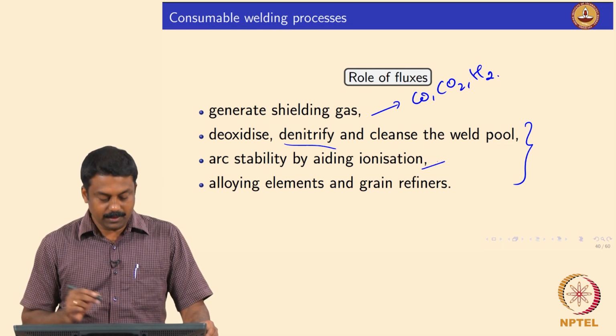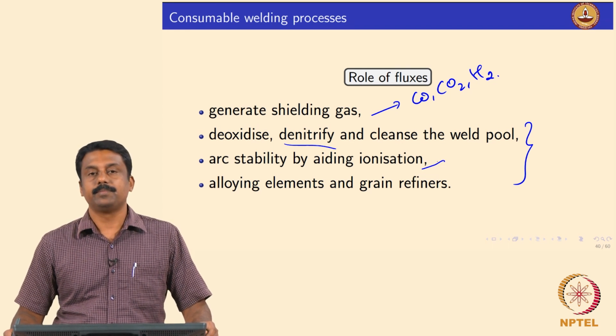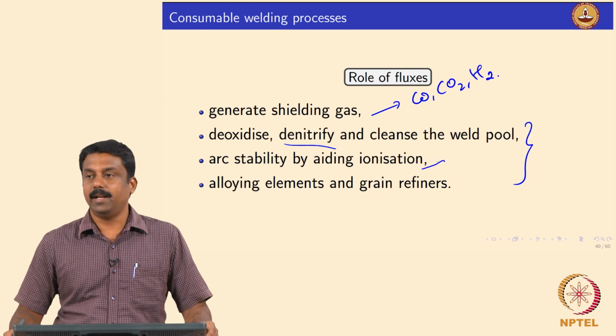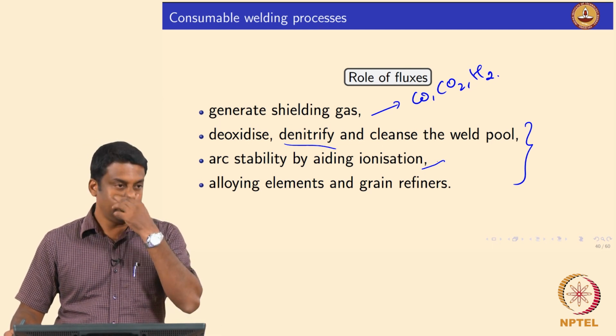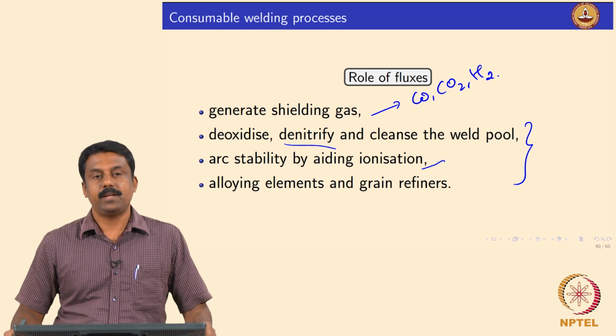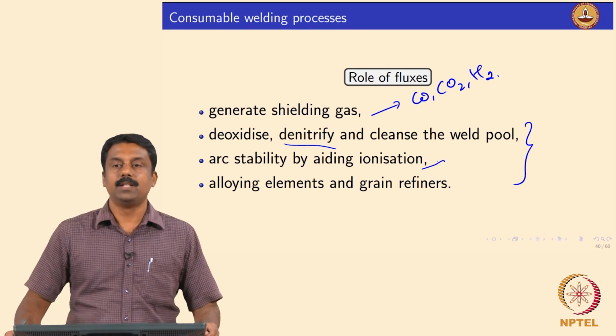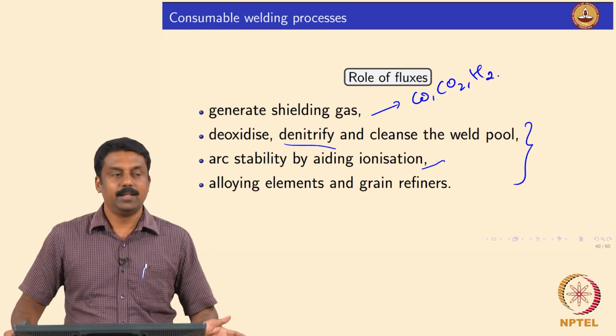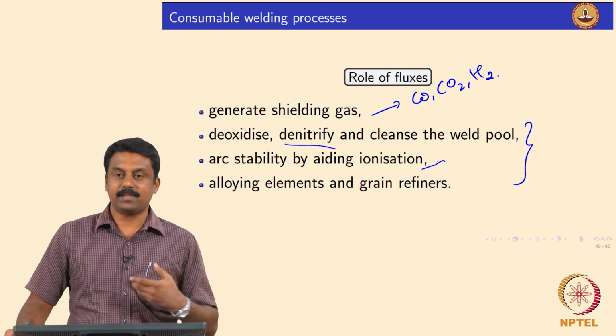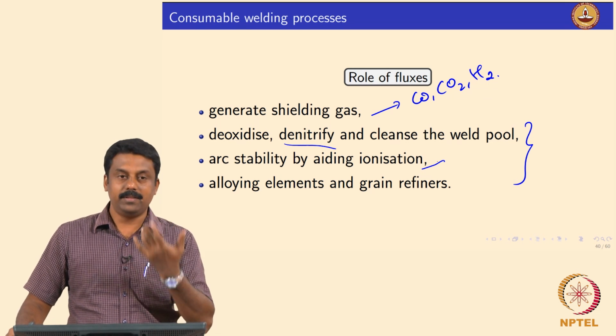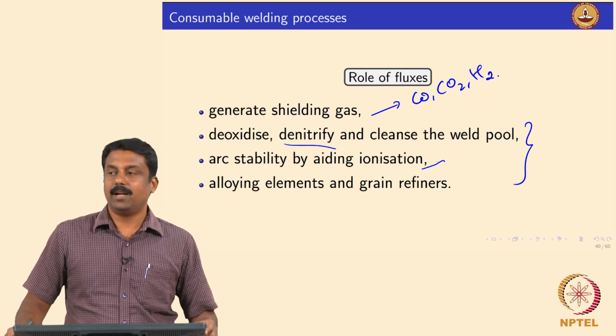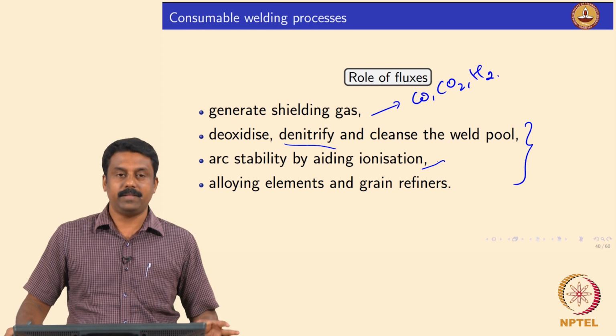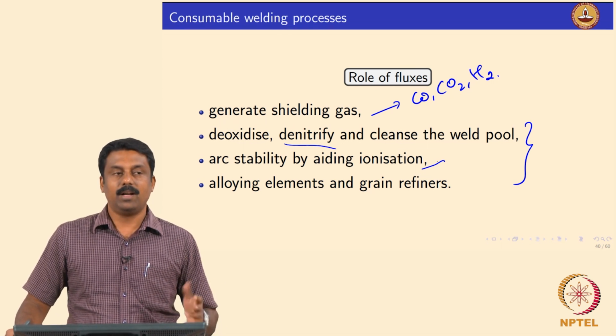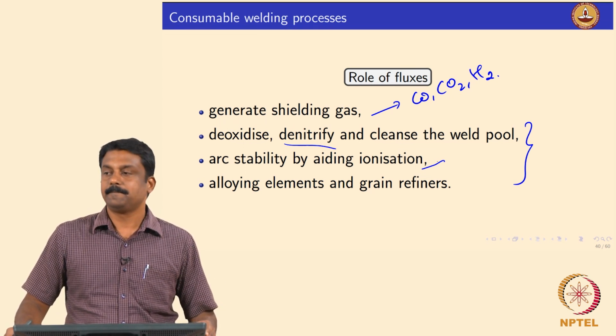and then to improve the arc stability, because we know that the oxides have very low ionization potential. So, they also promote ionization. So, if you improve the ionization, obviously arc stability increases. Again, ultimately the basic definition of arc is sustained discharge. So, discharge is sustained to have a stable arc. So, if you promote ionization by adding oxides, arc stability increases automatically.